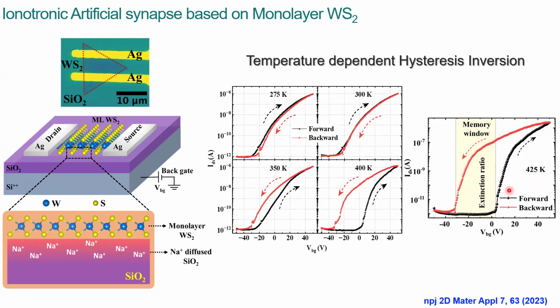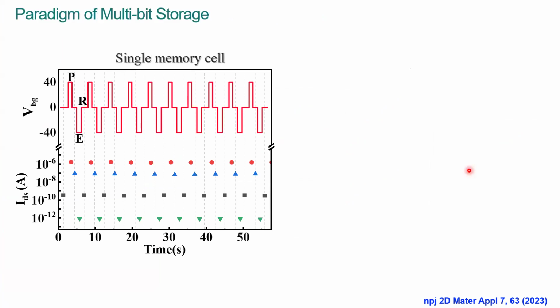This is the forward direction, and when you go in the backward direction using these transport characteristics, you see an increment in the conductance states. This is because of the movement of Na+ ions towards the channel at positive gate voltage, which additionally dopes our 2D material, so the conductance of the 2D material rises as the Fermi level is rising. And the vice versa happens if we go to negative gate voltage. You are moving the Na+ ions away from the 2D material, so it will decrease the conductance of the 2D material.